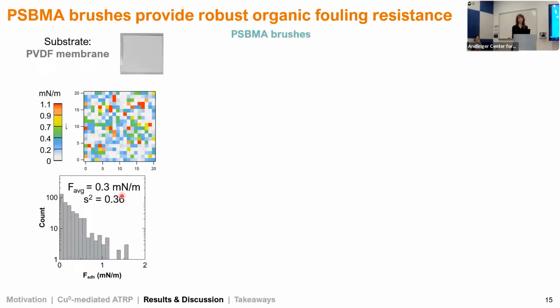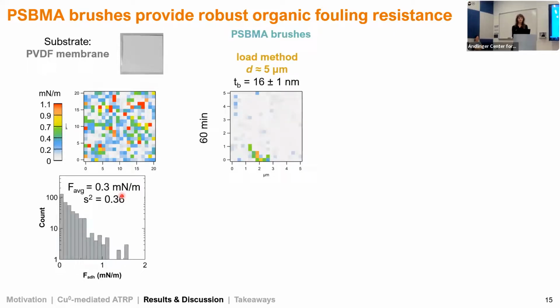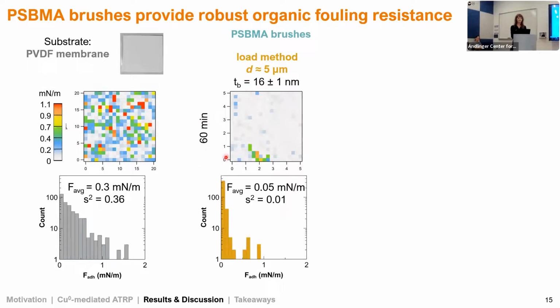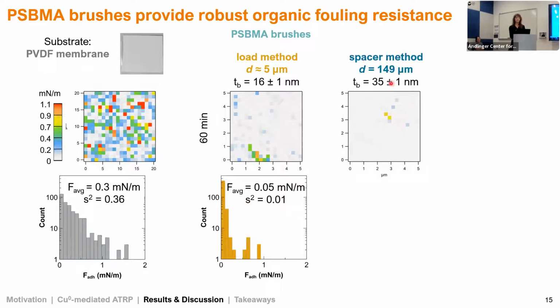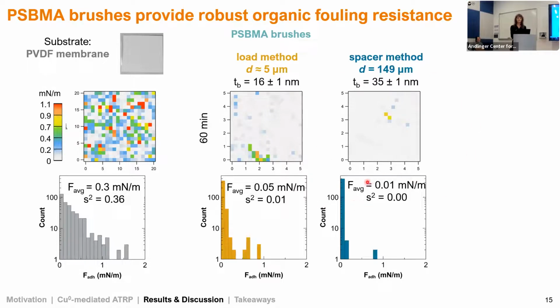So after modification with our brush layer, starting again with the load method, we have a brush thickness that's relatively thin, about 16 nanometers, but we've improved fouling resistance dramatically. We can see this quantitatively: we've reduced the adhesion force by an order of magnitude, and variance is also close to 0. So that's looking good. For the spacer method, if we increase D and we also increase brush thickness, we see a further improvement in fouling resistance. The average adhesion force has gone down a little bit further, and variance is also almost equal to 0.